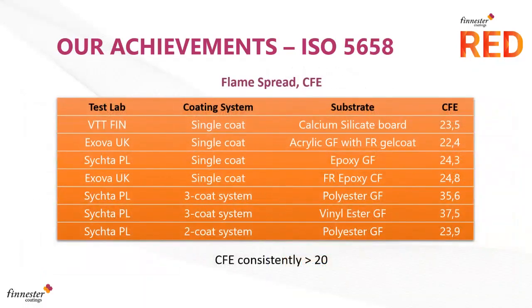But we shouldn't overlook the other requirements in the standard, and a very critical one is the flame spread, the critical flux of extinguishment, the CFE number. We've worked on that on many occasions, and as you can see, we've done a considerable amount of testing here with different test labs, and we're consistently above the number 20 for this parameter, demonstrating that we're meeting the requirements for this type of application.